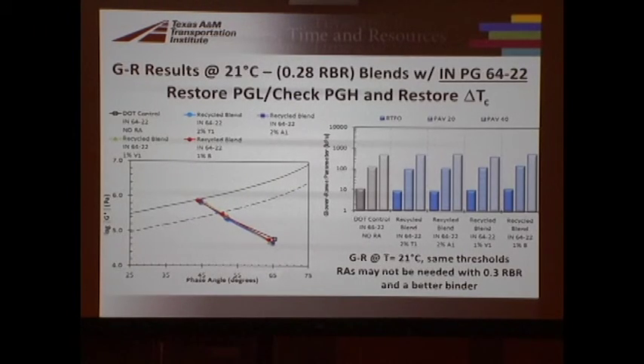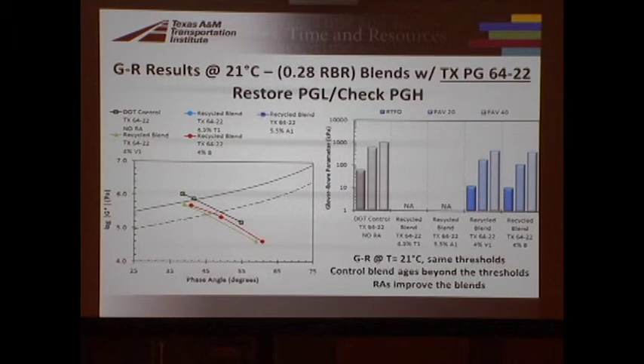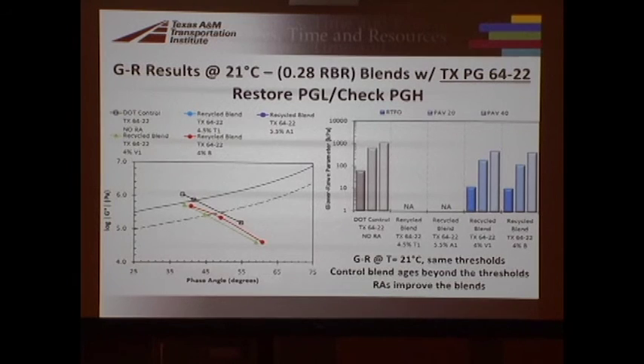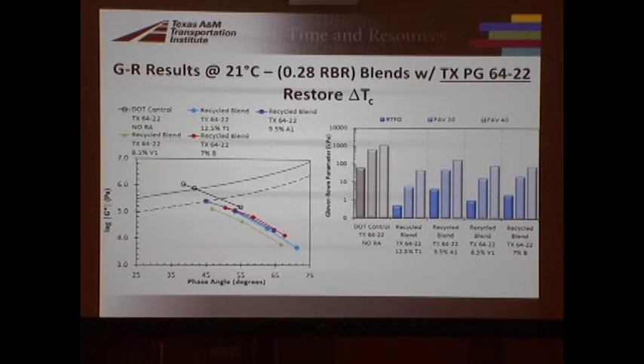But what we saw, and we changed the parameters for this black space to 21C, which is more applicable for a 64-22. So everything is kind of shifted already. The Indianas, it doesn't make a difference. At those low recycling agent dosages, it doesn't make a difference. With the Texas, though, we do see that this is the initial values at 21C, so everything just kind of moves down and to the right. But when we up those dosages to 12.5, oh my goodness, we're way down here, and we're probably over-softening.